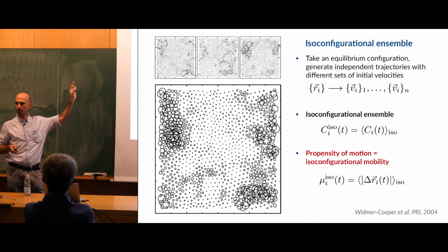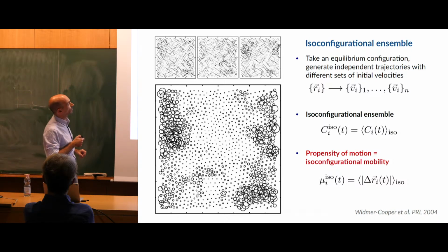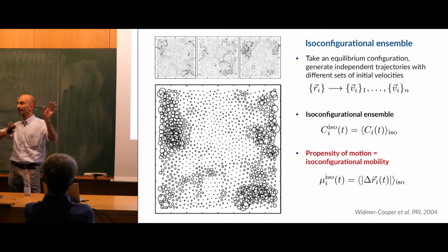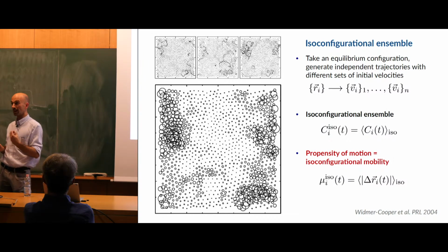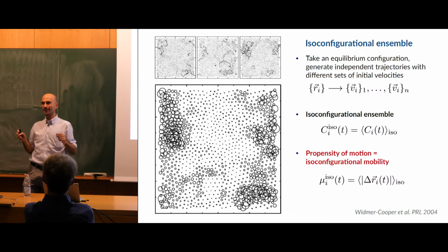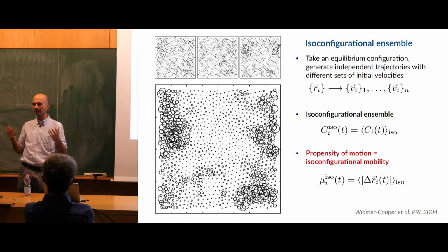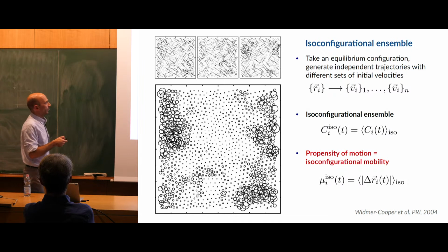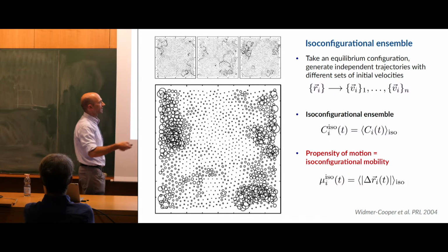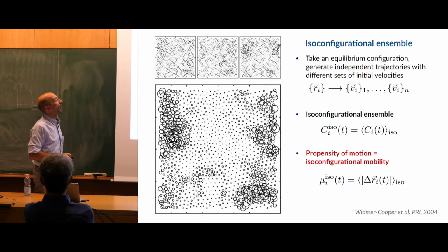So the original intuition by Peter Harrowell was the following. I take one configuration, I start many independent MD trajectories, and what he realized was that the heterogeneities that you get in the dynamics are slightly different from one another every time that you start a new simulation. So we should get rid of this dependence on the momenta if we want to make a connection between structure and dynamics. And this is where the idea started. So you take the configuration, run many independent runs, and then average the results of the displacement after some time over all these trajectories. And this gives you the propensity of motion.